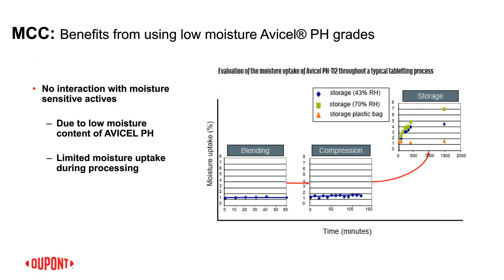There are certainly benefits of using low moisture MCC. For example, if you have a moisture sensitive formulation, you might want to start with a low moisture MCC grade, such as Avicel PH 112 or Avicel PH 200 LM. Or there are a couple more low moisture Avicel grades available. The water activity of this low moisture MCC is lower than regular MCC grade. And this can help to minimize the moisture interaction with API and increase drug product stability.